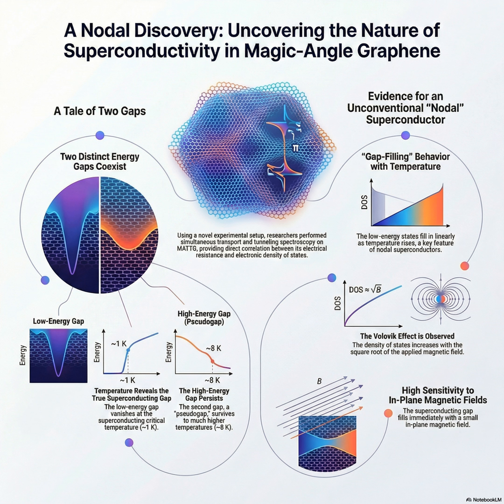Because in superconductors with nodes, applying that perpendicular magnetic field creates these quantum vortices, tiny whirlpools of current. And those vortices interact specifically with the existing nodes in the energy gap. Okay. And theoretical models, including ones from Volovik, showed that only a system with a nodal order parameter, a system with those pinholes, will generate a change in its density of states that follows that exact square root relationship. It is the absolute gold standard for confirmation.